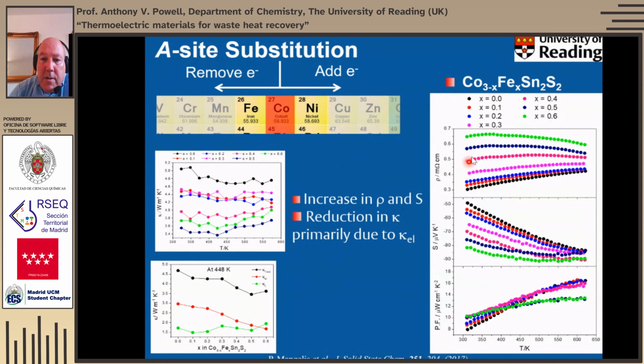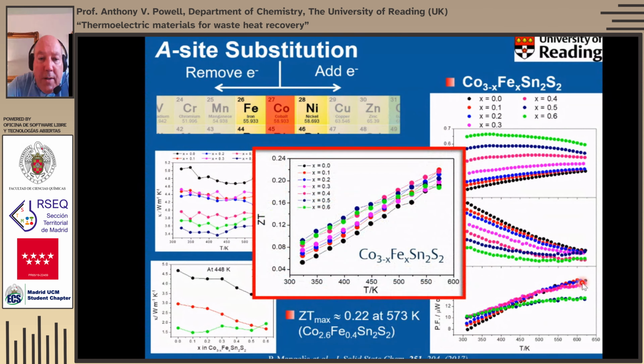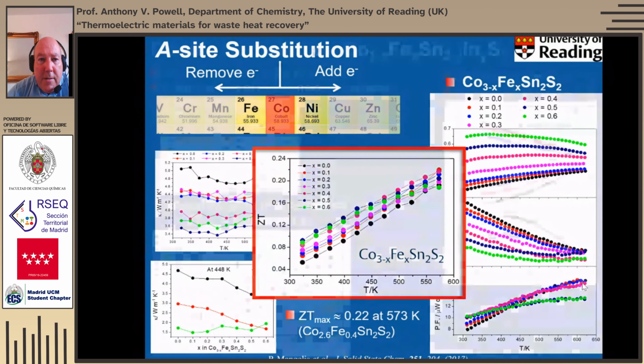So we see this resistivity rises, the Seebeck rises as well, coming down. It becomes more negative in this sense. But the important part is that the increase in the value of the Seebeck outweighs the increase in the resistivity, and consequently we find that we increase our power factor. And therefore, what we find is we actually get ZTs which are slightly improved, maybe not quite as much as they are when we tinker with the B site cation, the tin cation, but nonetheless, we can achieve a similar result by adjusting the electron count through the transition metal cations.